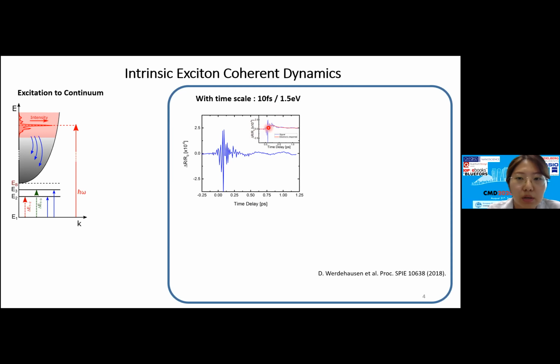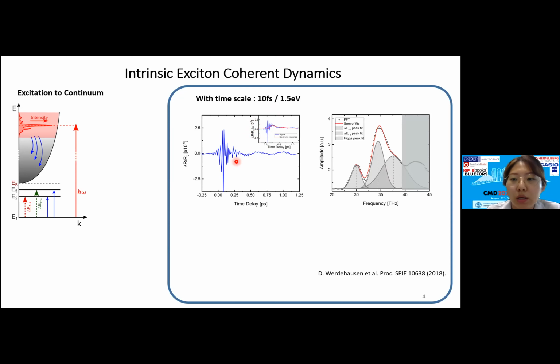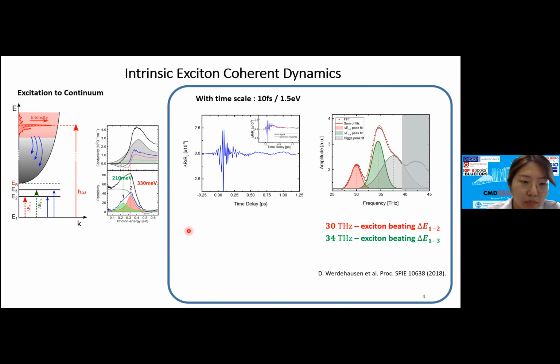At early times after the excitation, you can see this coherent oscillatory behavior, and the Fourier transform of this shows the collective modes, which are mainly three modes. The first two modes we call exciton binding modes, because the energies of these modes correspond to the different exciton energy levels. The remaining mode is at 38 terahertz, and this energy corresponds to the excitonic binding energy.